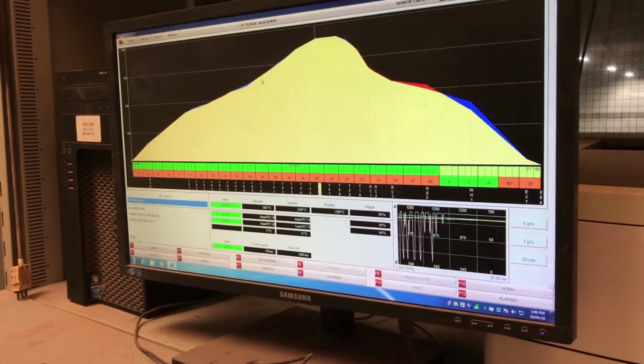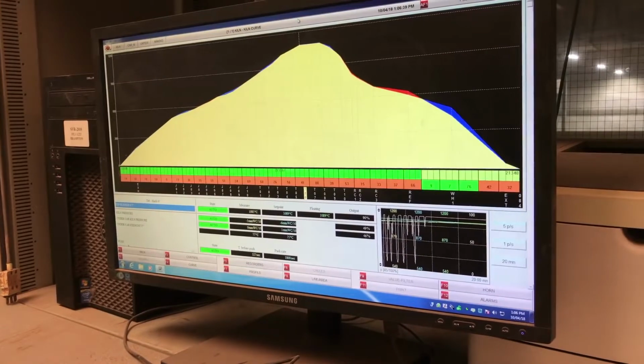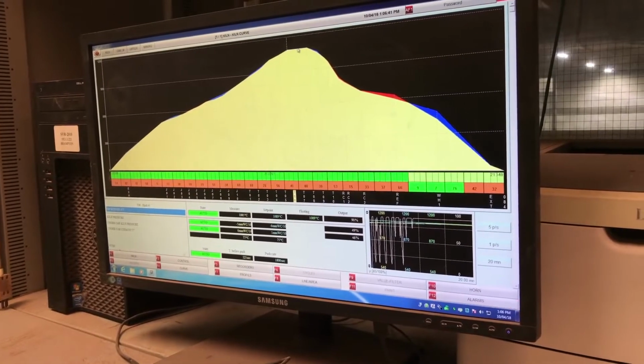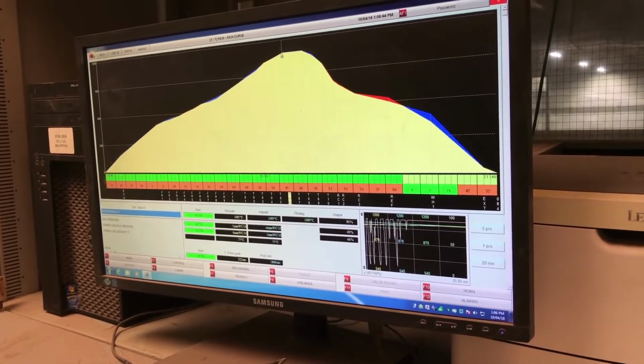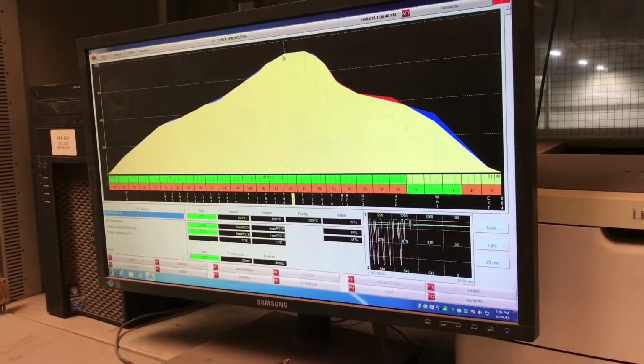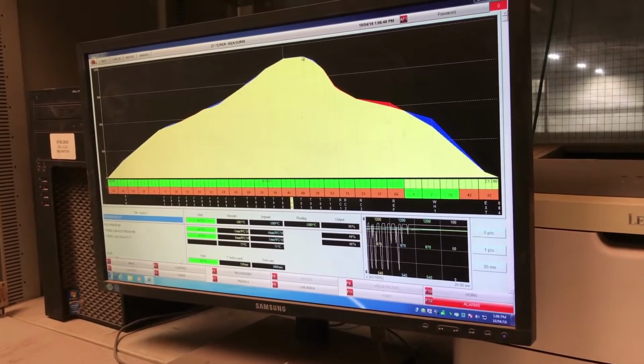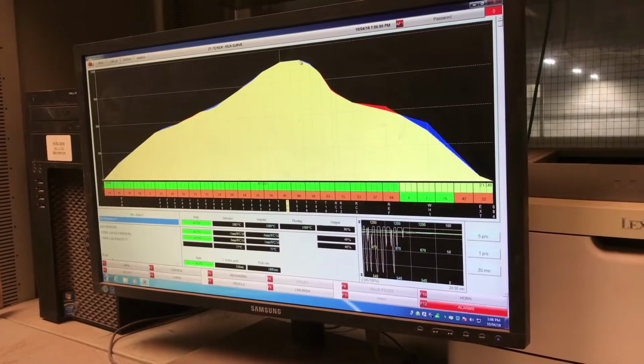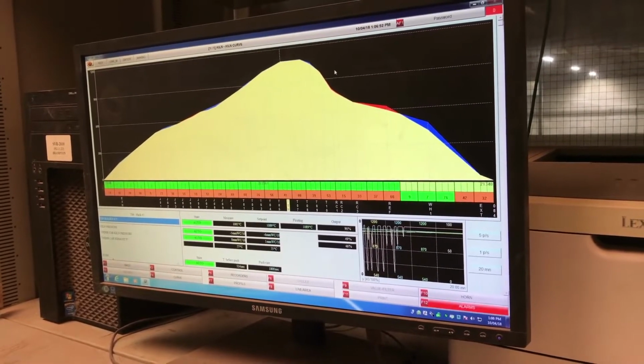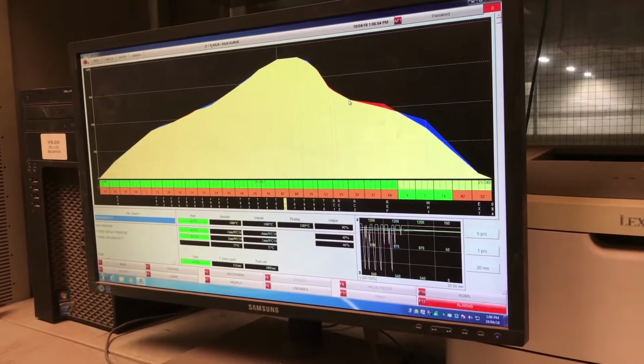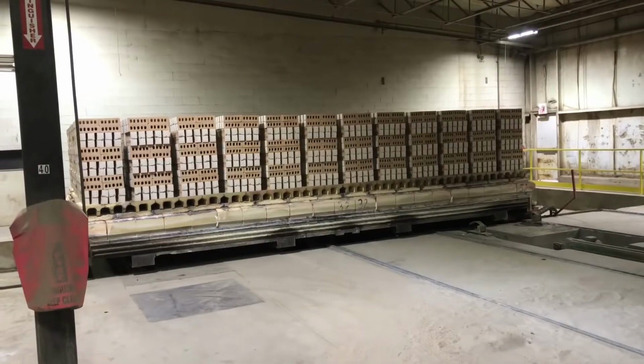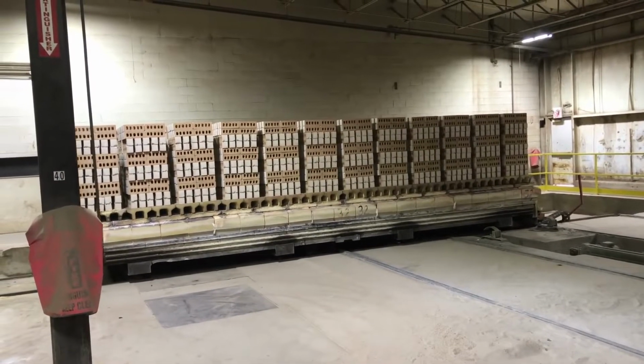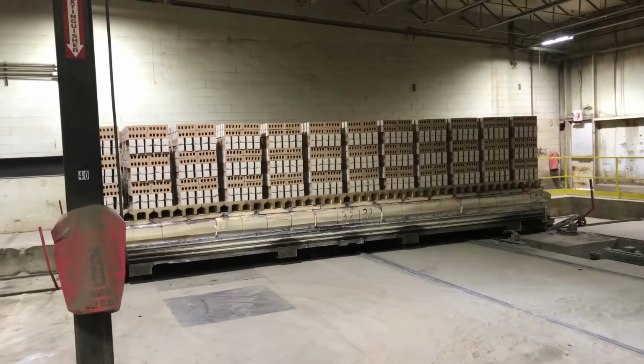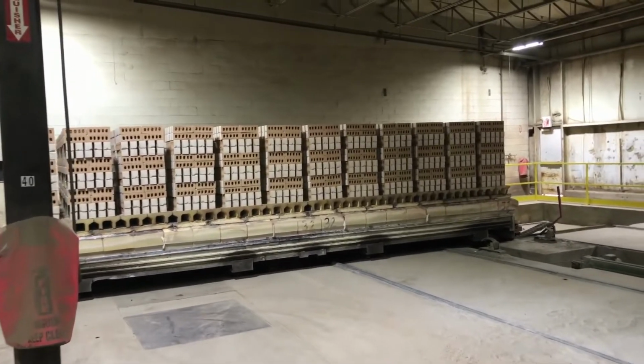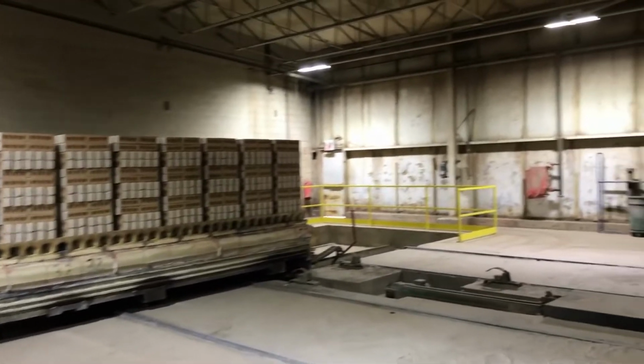This graph shows the varying temperatures within the kiln as a particular batch of bricks goes through. It's very important that the bricks be ramped up in temperature and then held at peak temperature for a minimum amount of time and then cooled off. Even the movement of the trolleys is computer controlled. And here you see a trolley that has just recently come out of the kiln that you see here.